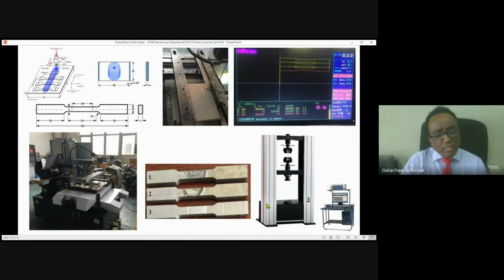After the weldment has been done, the characterization will start at this critical stage. Here you can see how the three dog bone samples have been taken by means of the wire EDM machine, and the other is for microstructural samples. In such a way, samples have been taken from the welded region. Then you can see how the cutting process on the wire EDM is being inspected on the monitor. So here is the wire EDM machine employed in this study. These are the dog bone samples ready for the tensile test, and this is the machine employed for the universal testing.